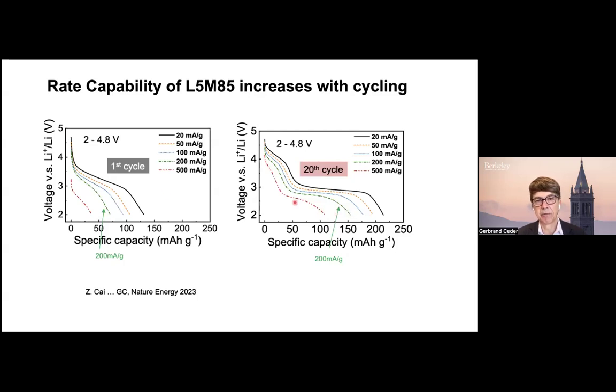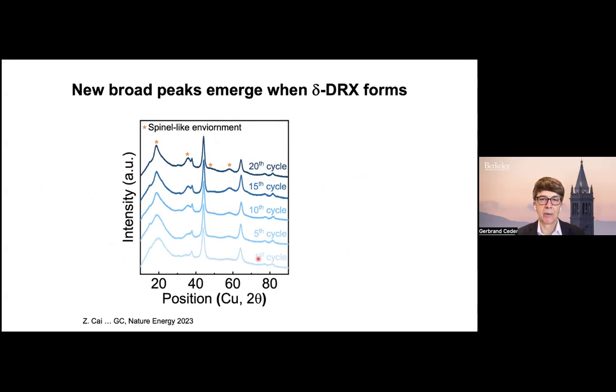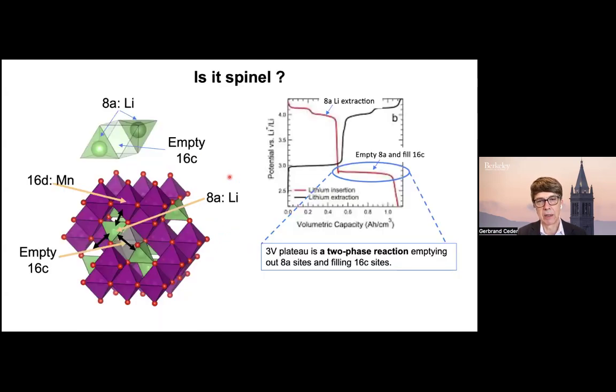But what you also see is that the voltage profile has transformed, has been modified from this sort of typical sloping profile of a disordered rock salt to something that has plateau-like behavior. And it turns out these aren't really plateaus. They never truly become flat, and I'll show you that later. They really are sort of more plateau-like. And if you look at the diffraction as a function of cycling, you see the typical rock salt peaks, but then with cycling, you see these things appearing that are certainly reminiscent of spinel. And so more generally, I would say they're reminiscent of cell doubling. So the rock salt unit cell doubles just like in a spinel. So the question is, have we actually made spinel by cycling? And I'm going to show you that not really.